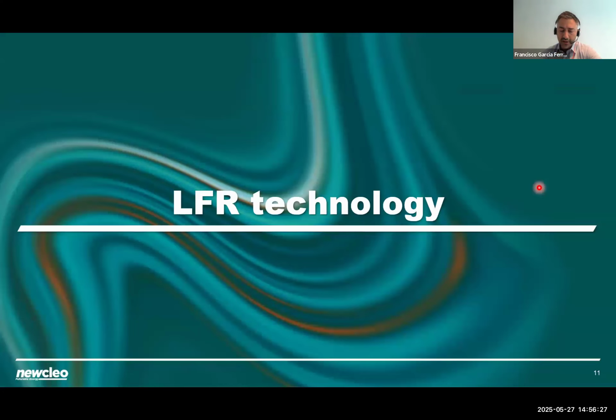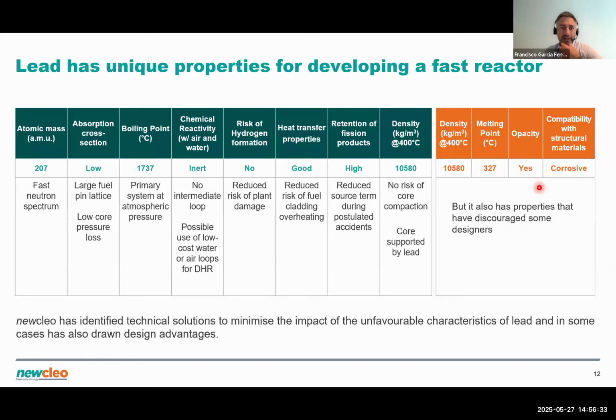Now, coming to LFR technology, I might not have to explain this in detail, but the use of lead as a coolant has many positive aspects related to the intention to close the nuclear fuel cycle, to achieve high efficiencies, to operate at ambient pressure, and have a very high safety margin. But it also has some drawbacks. It's opaque, we mentioned that. The melting point is relatively high, so that's something that needs to be managed. It's very dense, and it's also corrosive towards structural steels.